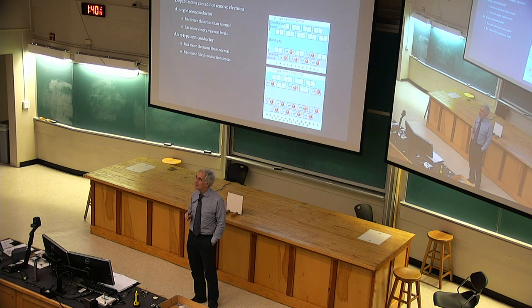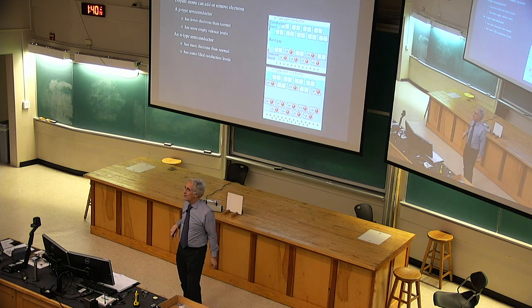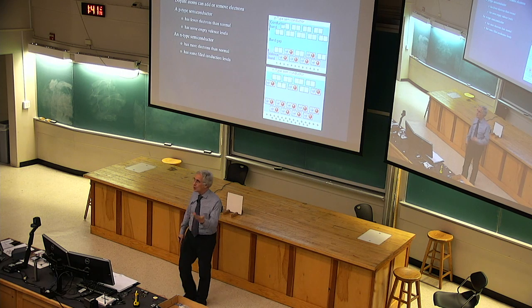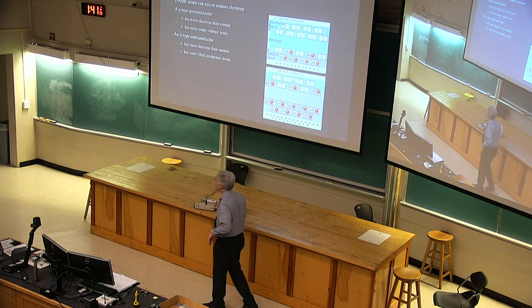So if you put that into the silicon crystal, it'll go in. You can put aluminum into a silicon crystal, and the crystal will still form, and it will be almost happy, but not quite. It's a little bit like, who brought these guys in here? We didn't invite them. Okay, so there they are. And it means as you're filling in the electrons to build this hypothetical solid again, you run out of electrons earlier than before. There just aren't that many electrons because the aluminums didn't bring in their fair share. And as a result, you get the same band structure for all practical purposes, but some of the electrons are missing in the valence band.